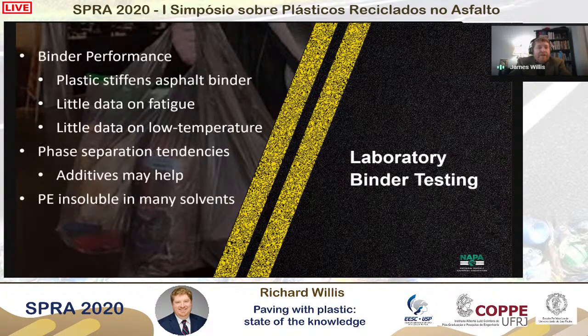When you look at binder performance, this is really important when you start looking at things like the wet process. As we expected to see, plastic stiffens your asphalt binder. However, there's really been little data that has looked at things like fatigue or the low temperature performance. Most of the studies looked at things like penetration, the softening point, the viscosity, the ductility, and some people started looking at performance grade.